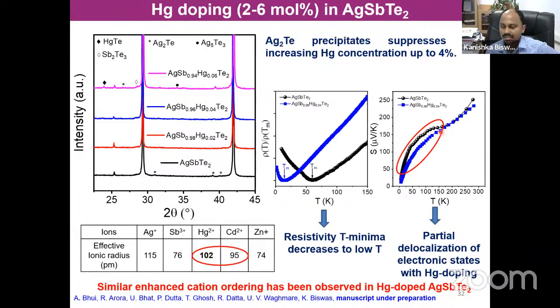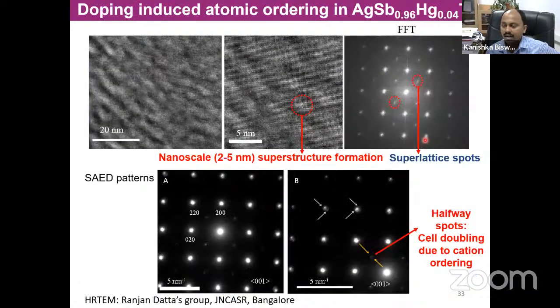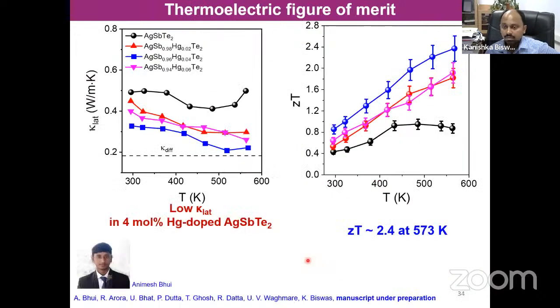And then we see the similar feature in the Seebeck coefficient. And we have collaborated with Ranjan Datta here, who is an expert in TEM. And you can see, we see a clear signature of ordered nanodomains. This is much more clear than the last one. And we can see the cell doubling as well as the superstructure spot, what we have seen in the cadmium. So we are writing this paper. And we measured a ZT of 2.4. So basically, what we proposed in cadmium can be generalized to mercury, and ZT is also very high. So that generalizes our concept, whatever we have given in cadmium doping in this compound.